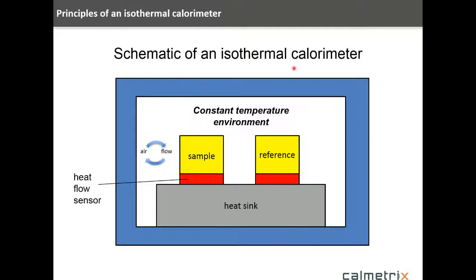This is a schematic of an isothermal calorimeter showing the primary components. Let's start on the inside of the instrument with the sample, which goes inside of a 125 milliliter sample cup. And I'll show you pictures of the sample cups here in a little bit. We typically run this instrument in a differential mode, so we're running a sample against an inert metal reference in a differential fashion. Both the sample and the reference are sitting on top of heat flow sensors, which are in turn connected to a large metal heat sink. This basically then constitutes the actual calorimeter, which is sitting inside of a temperature controlled chamber shown in blue here. And we can control the temperature in that chamber very precisely from 5 to 70 degrees C.